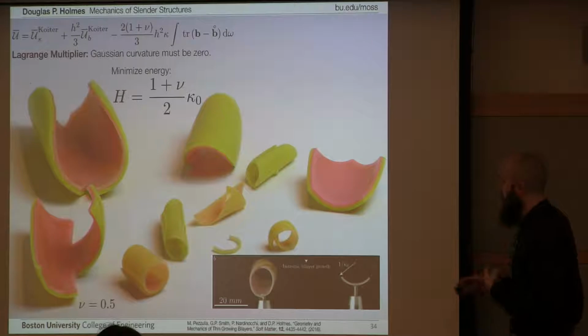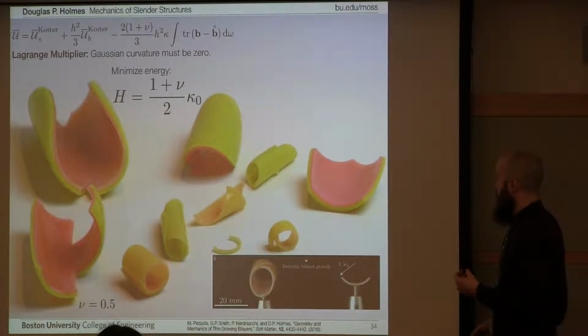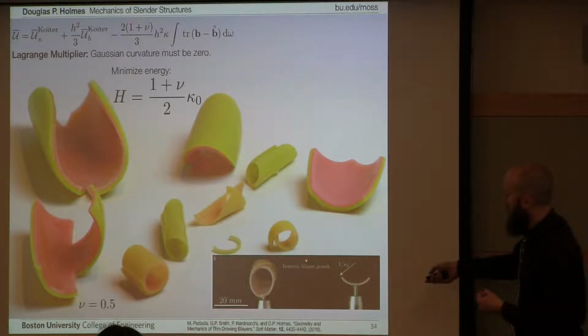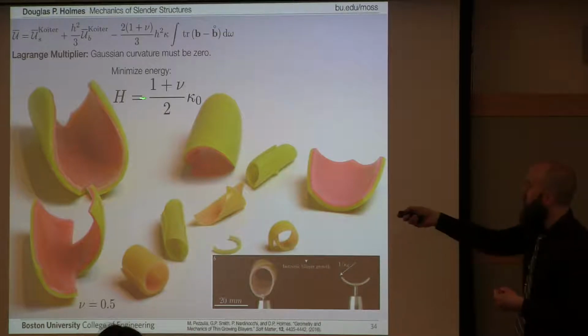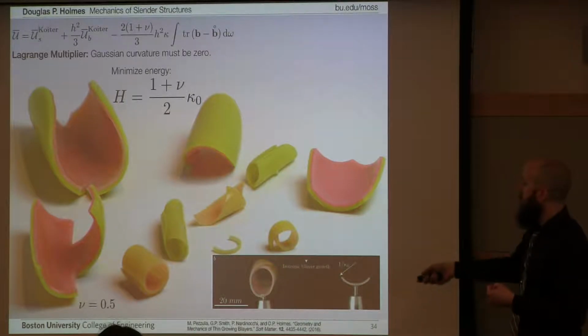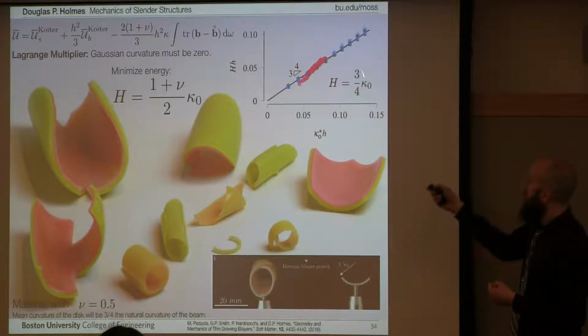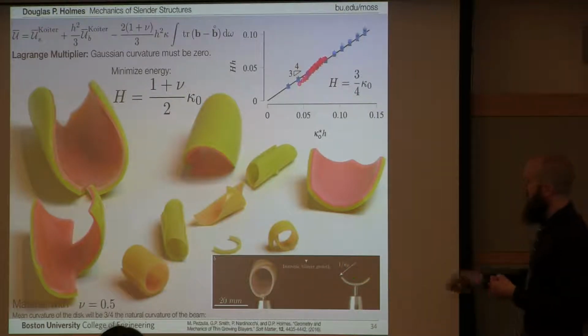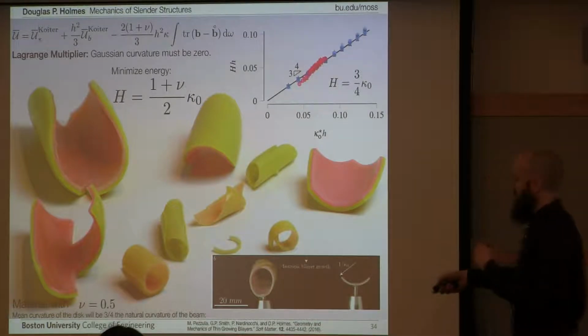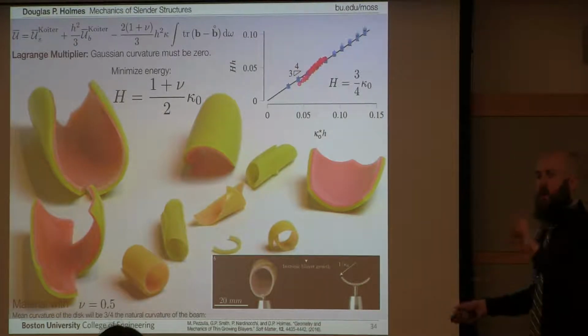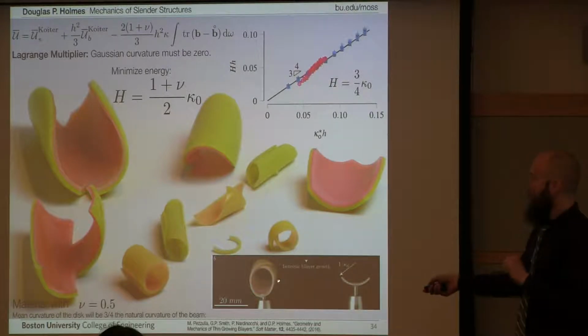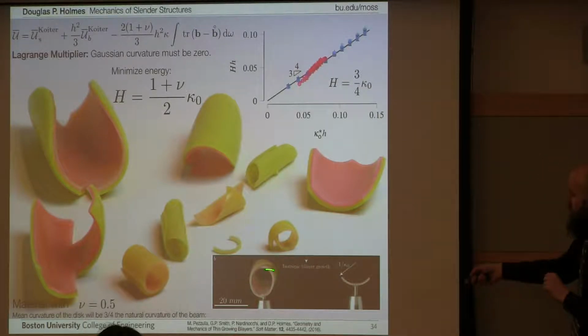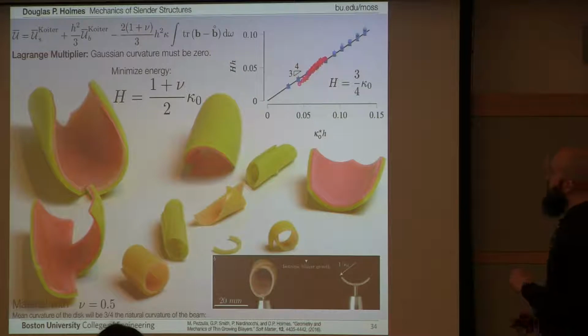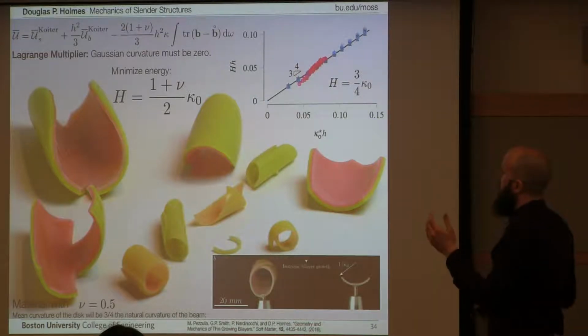And how we do this in the lab to confirm this measurement is we take a bilayer plate, doesn't matter the shape, a square, pentagon, circle, doesn't matter. And then we take a beam that's exactly the same shape, and we measure the curvature of this beam. And what this equation says is that the mean curvature of this shell should be 3/4 the natural curvature of this beam. It kind of looks weird, right? It kind of looks the opposite, doesn't it? It looks like this thing is actually more curved than this one. But that's because, remember, that mean curvature is the average of the curvature in this direction and 0. And so this is why the mean curvature here is actually lower than this one here. So this confirmed it.